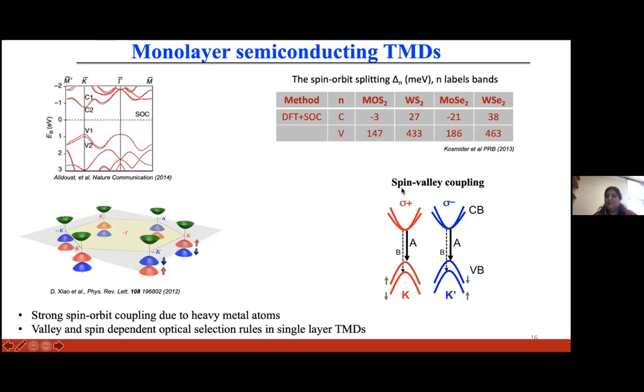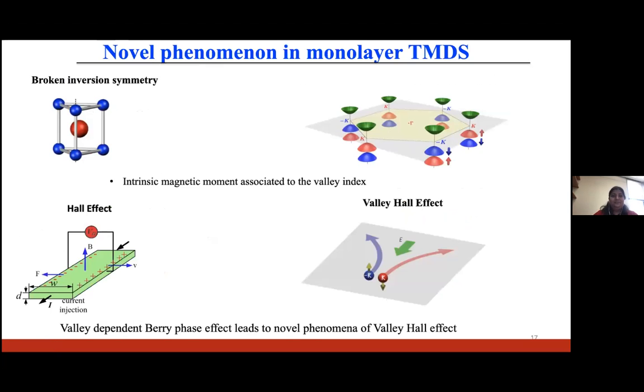And we have this spin valley coupling, which means that if we use light of positive helicity, then we can couple the carriers in one valley. And if we use light of negative helicity, then we can couple the carriers in the other valley. And in addition, because of the broken inversion symmetry in single layer TMDs, we can also have a novel Hall effect called the valley Hall effect.